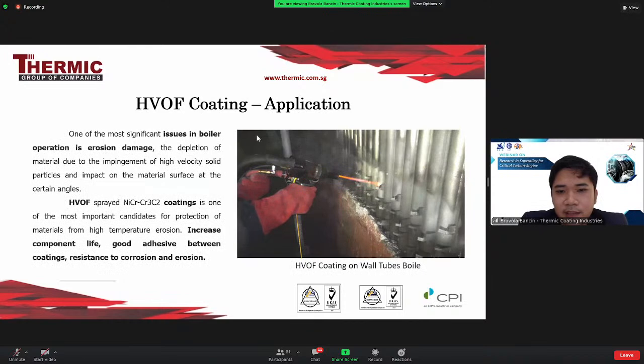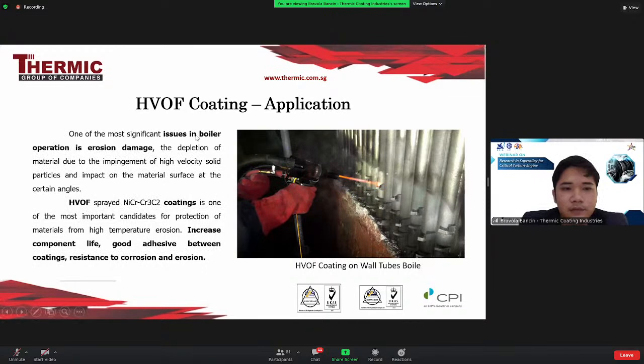Another application is HVOF applied to boiler wall tubes. One of the most significant issues in boiler operation is erosion damage. HVOF sprayed nickel chromium carbide is one of the most important candidates for protecting the material from high temperature erosion on boiler wall tube components. It has good adhesion between the coating and the substrate, and is resistant to corrosion and erosion. The material depends on the environment specification.